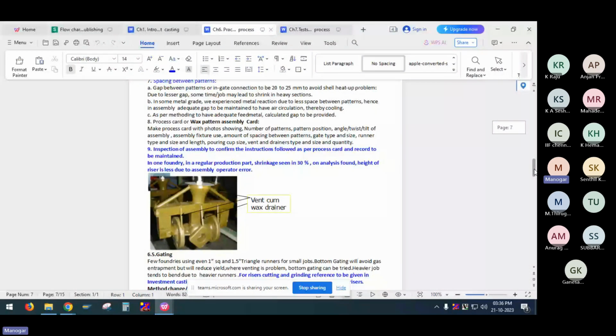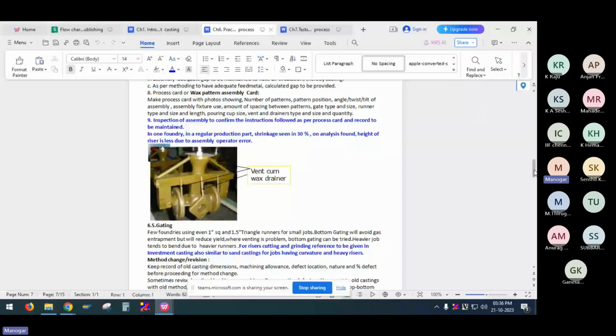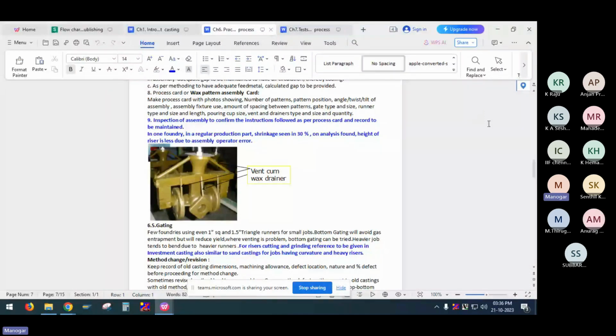And inspection of the assemblies. See, normally the foundries make a sample and prove it, then the operators do the assembly. Even though they are given a sketch, in some cases proper assembly does not happen, which leads to rejection. Only after rejection do people realize where the mistake is happening. So for that reason, like inspecting the wax patterns or castings, we should also inspect the wax assembly, whether the riser size, runner size, ingate gating size and proper location of the vanes are properly used. In one case, the operator did not keep the proper height of the riser, which led to shrinkage. In the sample it was okay because they kept the proper length as per the design. Afterwards, nobody checked, so it led to shrinkage.